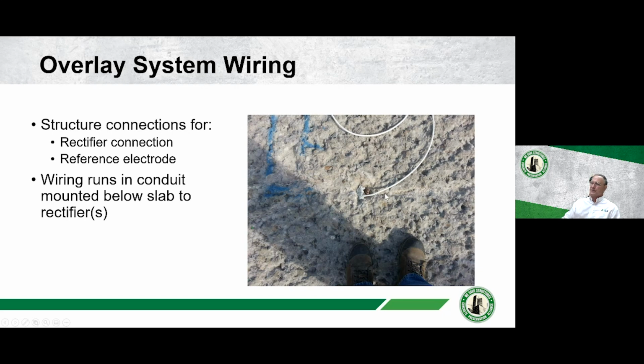Structure connections are just simply this. It's just a wire; you find the reinforcing steel, they connect it to the reinforcing steel, and then they fill it with epoxy. You fill around the connection with epoxy so that no moisture can reach the copper to steel connection and cause a corrosion cell, a little mini corrosion cell right at that connection. And then you cut a slot and you run these wires through conduit down below the slab.